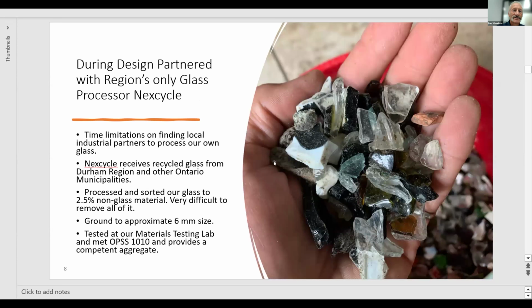During the design process, we partnered with the region's only glass processor, Nexcycle. Time limitations on finding a local industrial partner to process our own glass made us turn to Nexcycle. They receive recycled glass from Durham Region and other Ontario municipalities. They processed and sorted our glass to 2.5% non-glass material. It's very difficult to remove all of it. It was ground to approximately 6 millimeter size, which was ideal for our application.